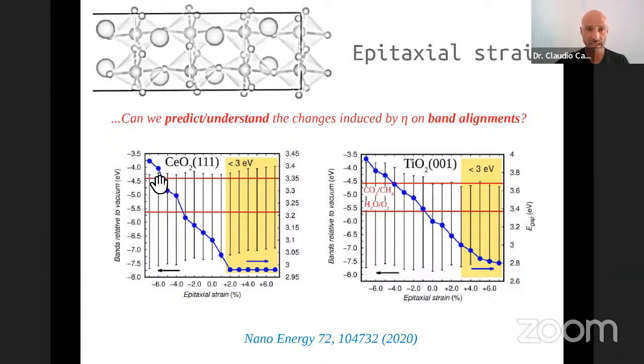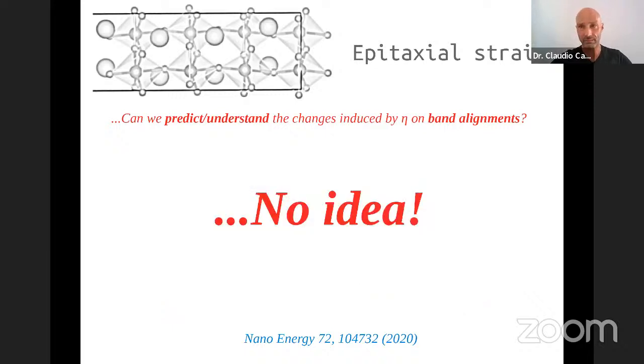So here, for instance, the band alignments tend to go higher in energy as you move from the compressive to the tensile strain side, whereas in titanium dioxide, it's the opposite, right? So you go from higher to lower, right? So to the question, can we predict and understand the changes induced by epitaxial strain on band alignments? At that time, the honest answer would be no idea, right?